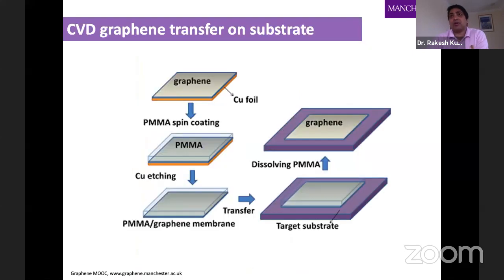graphene for electronics. So once the graphene is synthesized, the way the graphene is used for application, especially for electronic devices, we need to transfer it onto a solid substrate or even a flexible substrate, because it's synthesized on a metal substrate. You really need to transfer in order to make devices. So the common method that they use is called the graphene transfer method. You need to protect the graphene with some polymer and then etch away the metal film underneath through wet etching, and then it's transferred onto the target substrate.